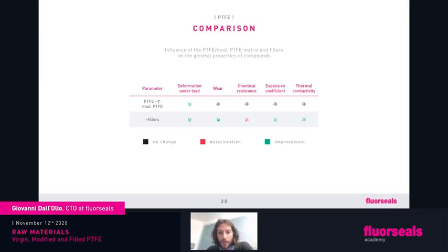Thermal conductivity, again, is an improved feature of PTFE plus filler. I want to spend very few words on it. Virgin PTFE is an insulant. A lot of the time it's used because of this property, but many other times, the filler inside the PTFE that gives a higher thermal conductivity is the key feature for the application. For example, on car engines, we have seals on the fuel injector. These seals are usually made of carbon or bronze compound, because they will see a very high temperature, sometimes 350 degrees. Virgin PTFE, after years and years, will start suffering. With the addition of a thermally conductive filler, it will help to see the temperature, but also to release this temperature. And this is really important.